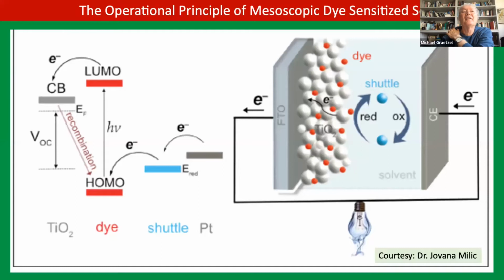And the cell itself is shown here. So we have those sensitized nanocrystals. Electrons are selectively collected from the excited state of the dye. Then they travel to the transparent conducting glass contact, and then in the external circuit they are doing work, and then you have to bring them back to the sensitizer. Otherwise, you would deplete the sensitizer. So you need some shuttle, which could be a redox electrolyte or some hole conductor, to get those electrons back to the dye. And so it's a simple device. School children can make it, and they can use natural dyes like from raspberries or hibiscus tea to make a solar cell.